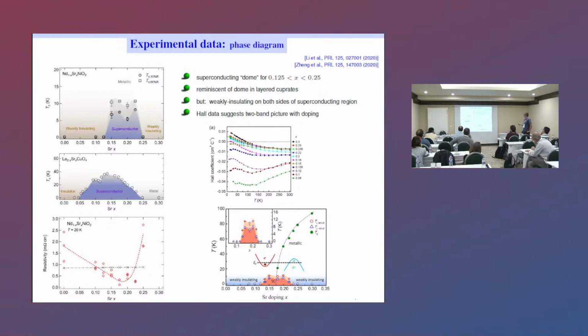However, there are some differences, in the sense that here we have a decent insulator, but then we have a pseudogap phase that is found. It also still has some metallic-like transport. It's complicated, but it's metallic-like transport, whatever. And here we have a nice metal, a Fermi liquid, in the overdoped regime. It's quite different in nickelates. Here it's weakly insulating in the overdoped region. This might change a bit, but it's still not as good, even with the newer samples, as in the cuprate. So there's something else going on.